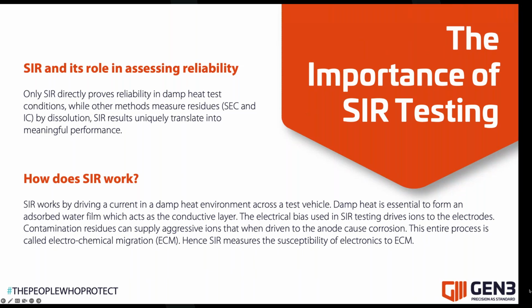So the SIR works by driving in a current in this damp heat environment, and it's essential to form this adsorbed water film, which acts as our conductive layer. The electrical bias used in SIR testing drives these ions back and forth to the electrodes, and contamination residues supply an excess of aggressive ions, which help that current to flow between the two electrodes, causing corrosion. The whole process is what we call electrochemical migration, and hence SIR measures the susceptibility of electronics to electrochemical migration. Next slide.